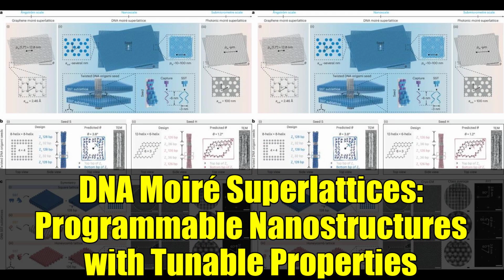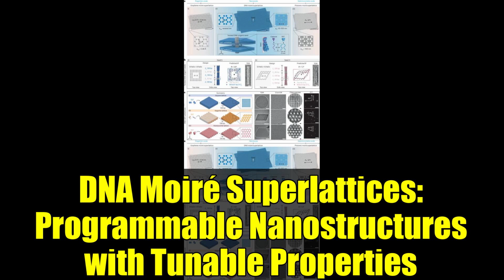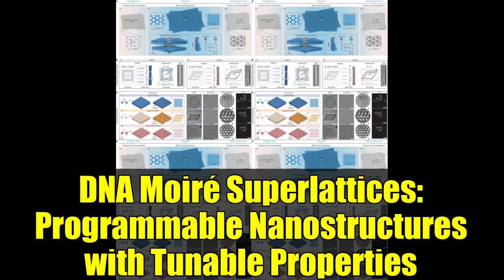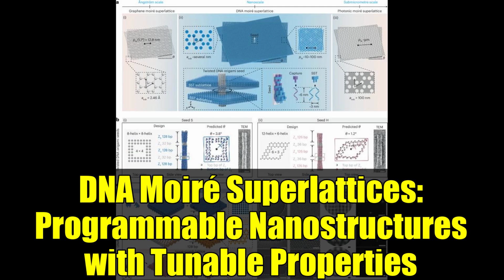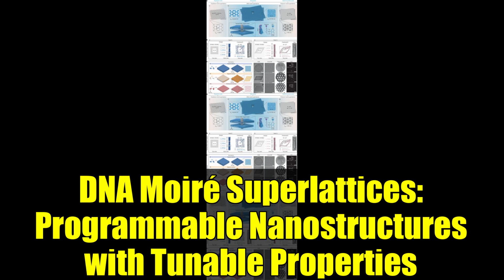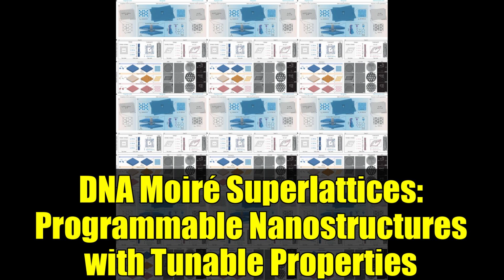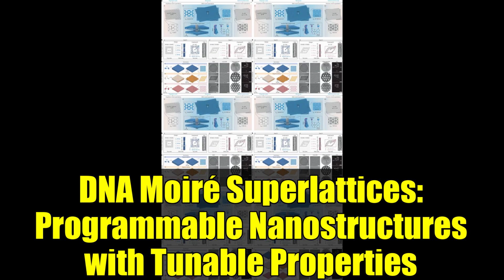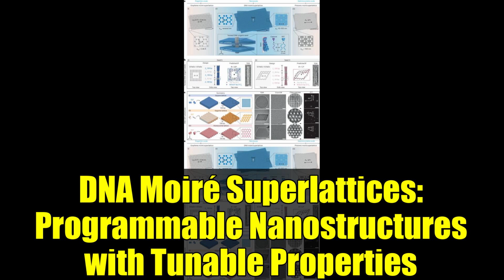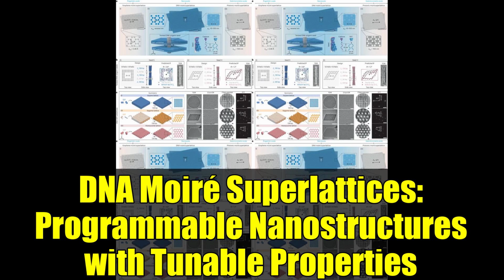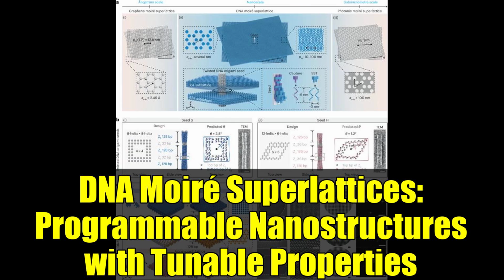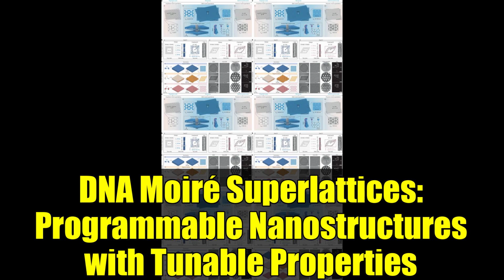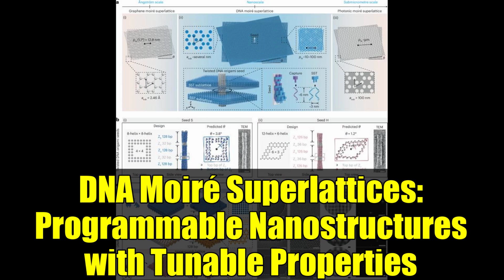Why does this matter? Imagine the challenge of painting a wall. If the first coat of paint sticks perfectly everywhere, the second layer goes on smooth. But if you have missing patches, the second layer will be full of defects. Similarly, only seeds with complete, continuous pairs of capture sites lead to robust, uniform bilayer assembly. Split up or scatter the capture pairs, and you get patchy, random growth. Remove them entirely, and you're basically back to square one, no better than letting the DNA tiles assemble willy-nilly. This principle was confirmed not just with square lattices but with kagome and honeycomb variants too, demonstrating a fundamental, symmetry-independent law of successful DNA-based Moiré superlattice assembly.